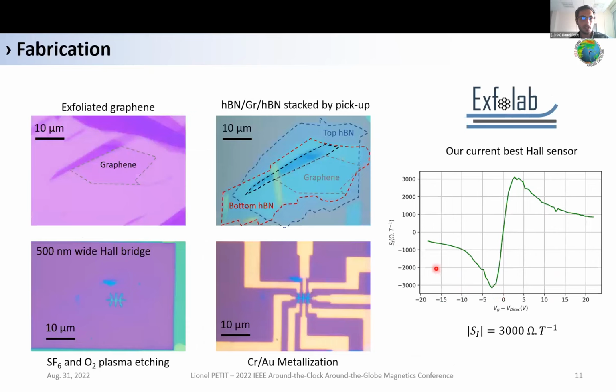In parallel of this simulation, I also build my own devices. I do that from exfoliated materials that I can stack using the hot pickup technique. Then I can etch the stack and contact it. And for now, my best Hall sensor exhibits a sensitivity up to 3000 ohm per Tesla, which is lower than the best one, but which is higher than the best epitaxially grown heterojunction structures.